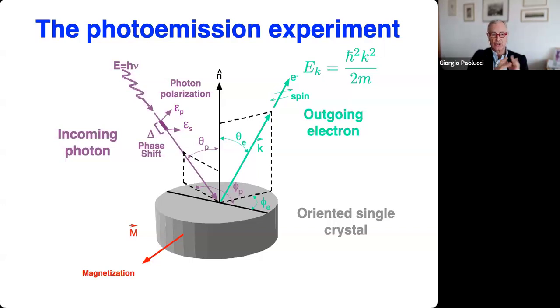You can apply magnetization if you wish to look at the magnetic details of the sample you're investigating. But basically, what you do is that you collect electrons which are kicked out of the sample, and you measure the kinetic energy, which is given by the relation you see in green in this slide. You can measure the spin as well in some sophisticated cases. I will not talk about spin-resolved photoelectron spectroscopy. You can change the polarization and look at different states.